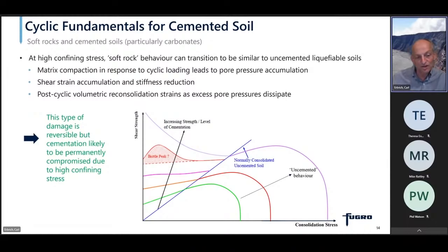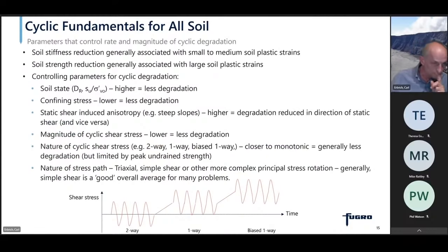So matrix compaction occurs in response to cyclic loading, which leads to pore pressure accumulation. That then in turn gives us shear strain accumulation and stiffness reduction. And we also then will get post-cyclic volumetric strains as excess pore pressures dissipate. And this type of damage is reversible, but cementation is likely to be permanently compromised due to the high confining stresses.